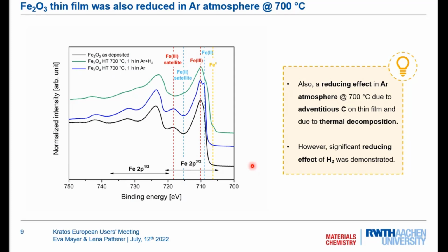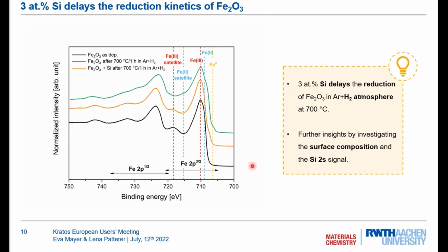Now we add some silicon into our sample. We have here a sample with 3 atomic % of silicon, which has a small shoulder here for the iron 2 oxidation state, but it is not as prominent as for the pure iron oxide sample. So silicon delays the reduction in an argon-hydrogen atmosphere, but to gain some further insights, we're going to look further at the silicon signal later.